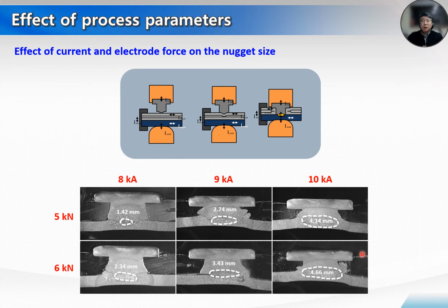At the same time, some formation of intermetallic compound can be expected, which will be explained further later. An excessive deformation of the element was also observed. This kind of excessive deformation of elements may cause a lot of pressing down of the element, which finally lowered or degraded the joint strength of each weldment.